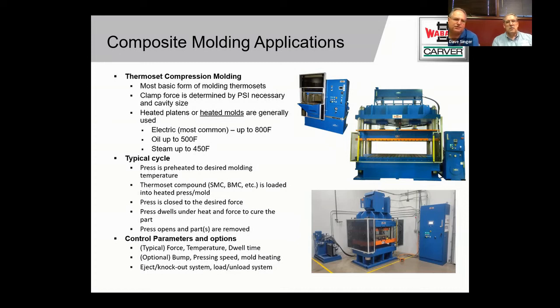So all these thermoset machines are heat only, and a typical cycle looks like what we've got listed there. Preheating of the platen or mold, inserting the thermoset material, whether it's bulk molding compound, sheet molding compound, some type of epoxy. Those are loaded into the mold. Press is closed for a desired time, and then it dwells there until the cure time is timed out.